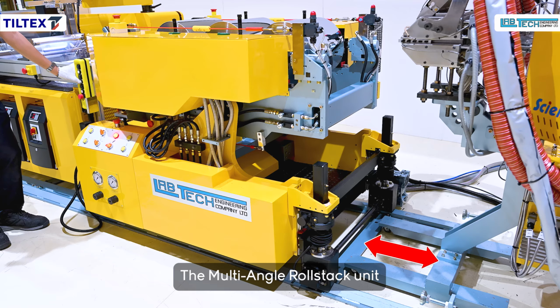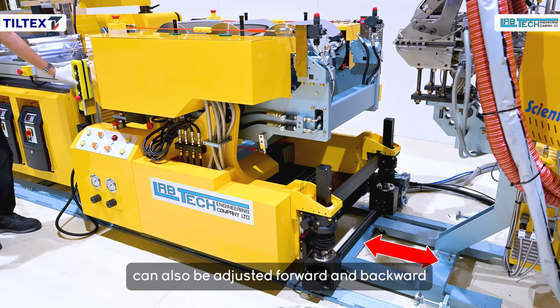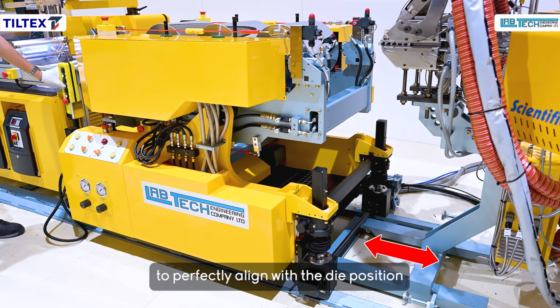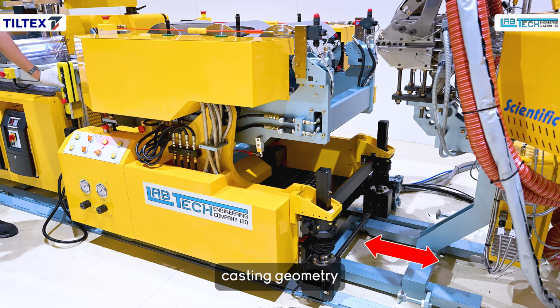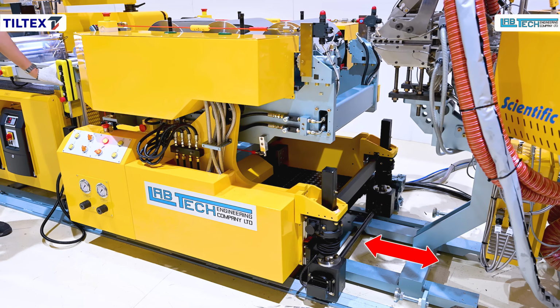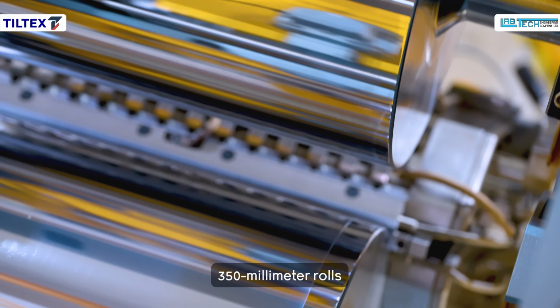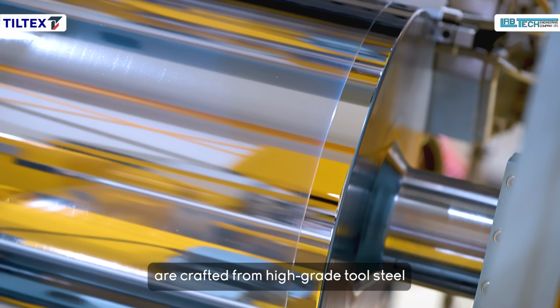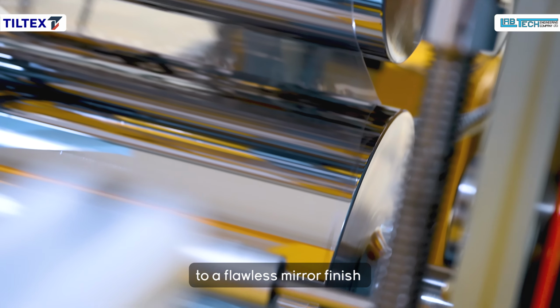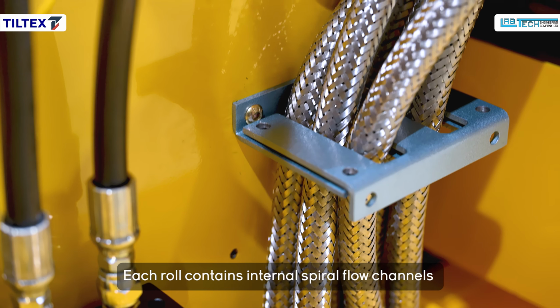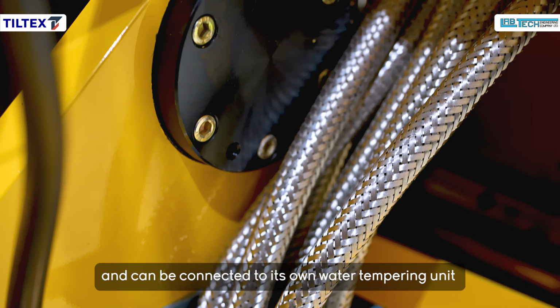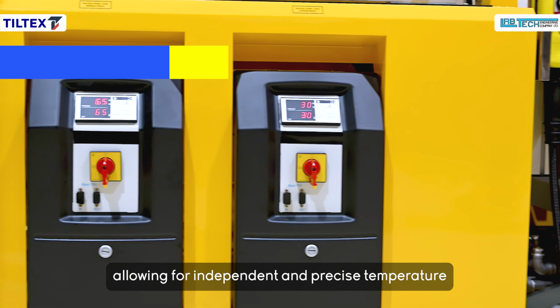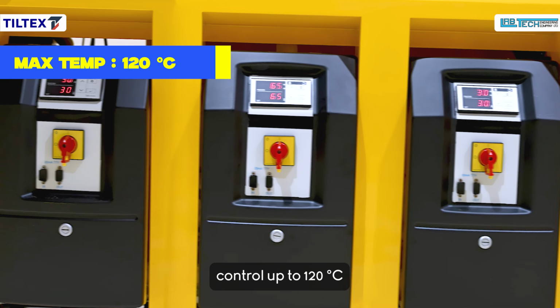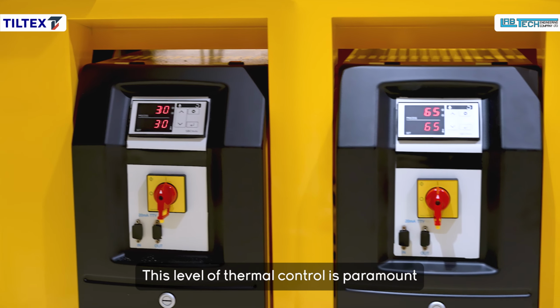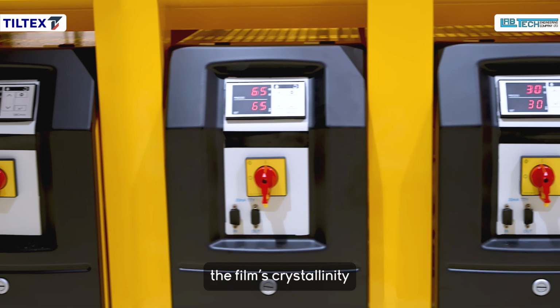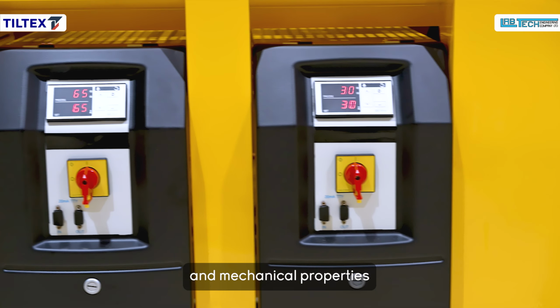The multi-angle roll stack unit can also be adjusted forward and backward by the control system to perfectly align with the die position, ensuring optimal film casting geometry for any configuration. The 3 large diameter 350mm rolls are crafted from high-grade tool steel and polished to a flawless mirror finish. Each roll contains internal spiral flow channels and can be connected to its own water tempering unit, allowing for independent and precise temperature control up to 120 degrees Celsius. This level of thermal control is paramount for influencing the film's crystallinity, clarity, and mechanical properties.